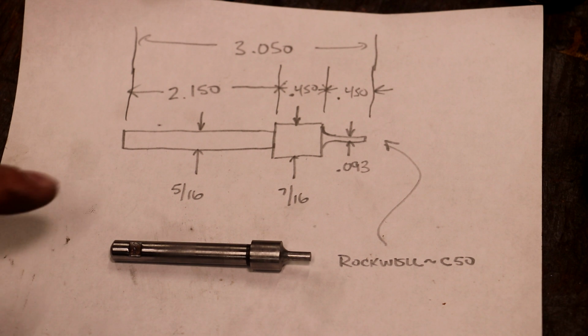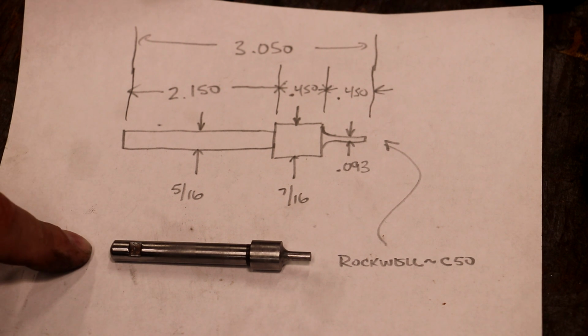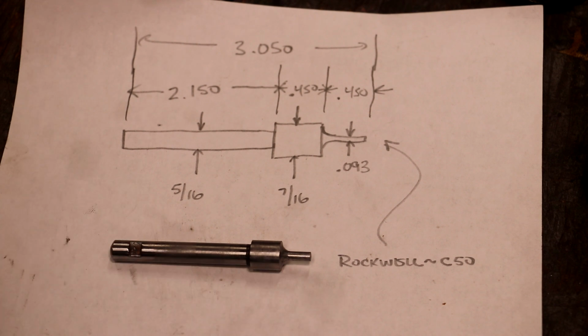I believe I can make this part out of some 4140. What I'll need to do is heat that end up red hot. I can probably just use a torch. It won't take much to get that tip hot, quench it in water, and then anneal it in my heat treat oven at about 500 degrees for 2 hours. And that should, according to the book, get me somewhere close to that Rockwell C50.